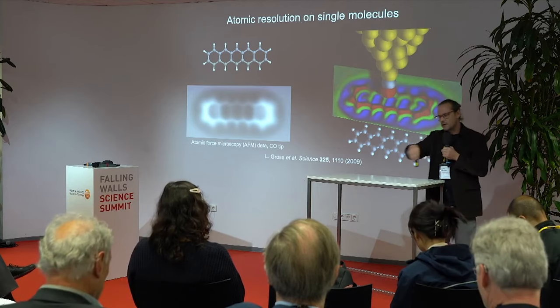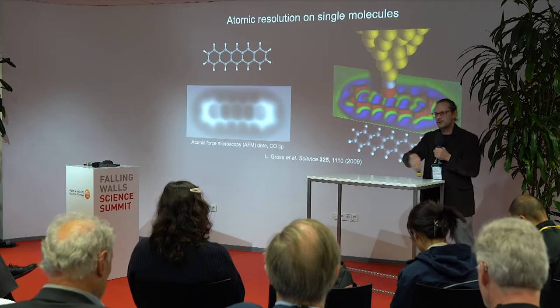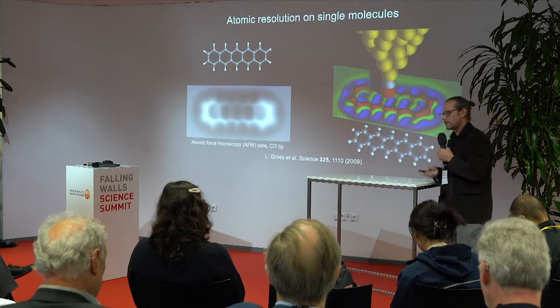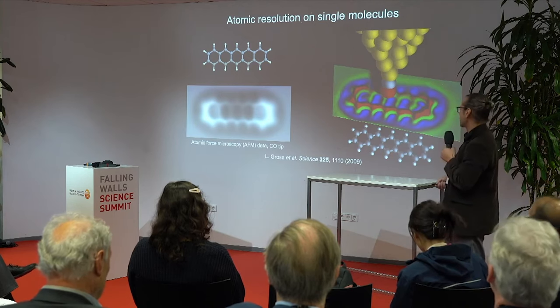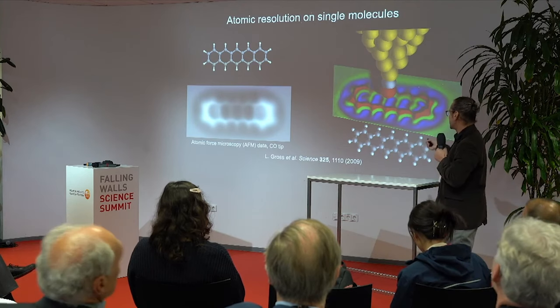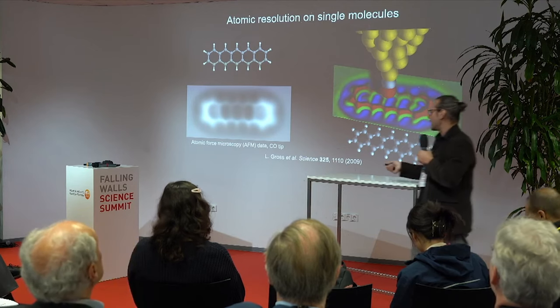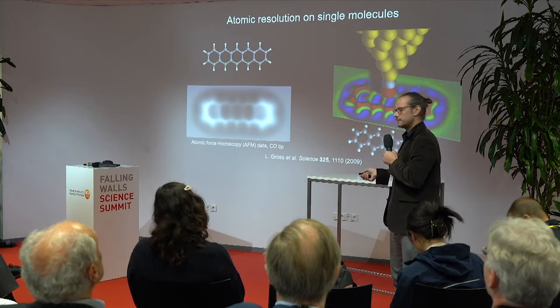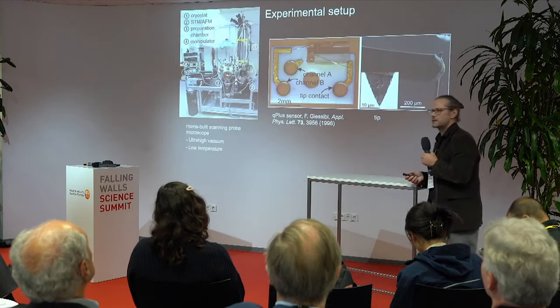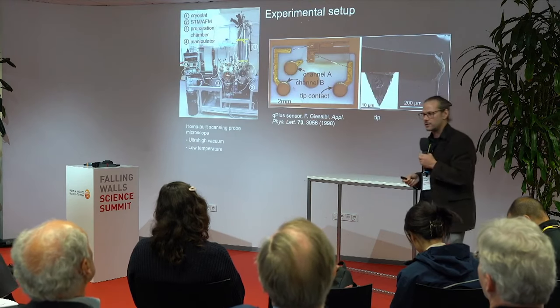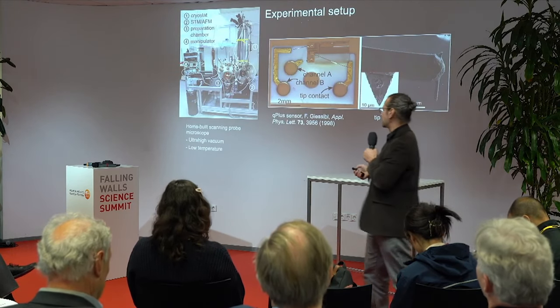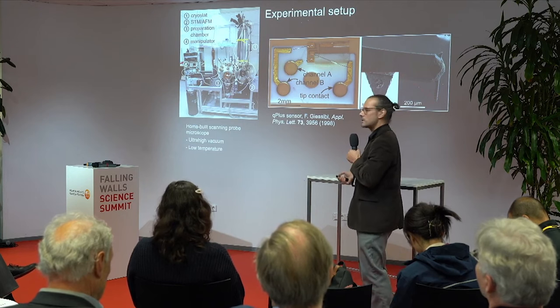In this technique, you raster scan this tip across the surface to get this image. And you record the force between this carbon monoxide molecule on the tip and the pentacene on the surface, and then you get these kinds of images. The next slide is just a little bit technical to give you an idea. So this is what our home-built microscope looks like.